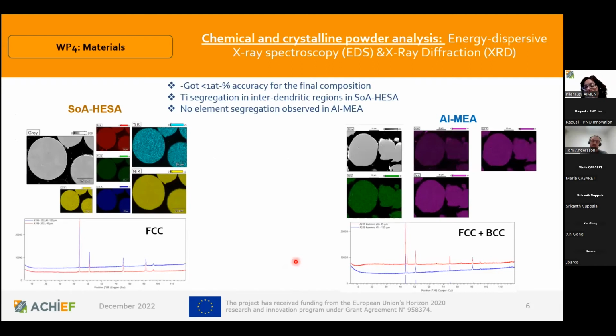Then we characterize the powder. So first we cut and polish the powder, and we make some EDX analysis in order to see the distribution of the elements inside the particle. And as you can see here, in the first material we have some segregation in the interdendritic region, and we have only one phase that is FCC. And in the other material, we have a much more homogeneous distribution of the different elements that compose the alloys. And using XRD diffraction analysis, we check that we have 2 phases, FCC and BCC.